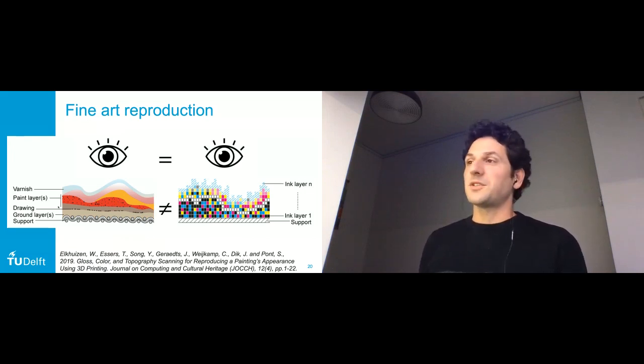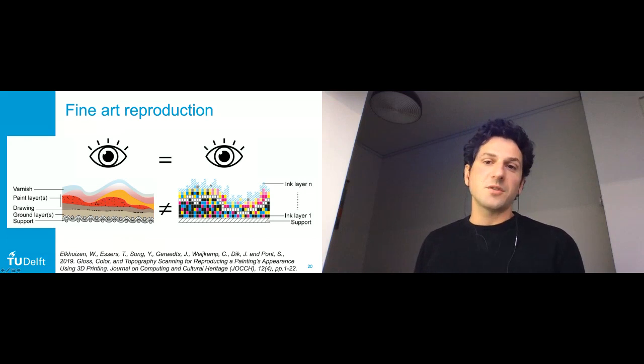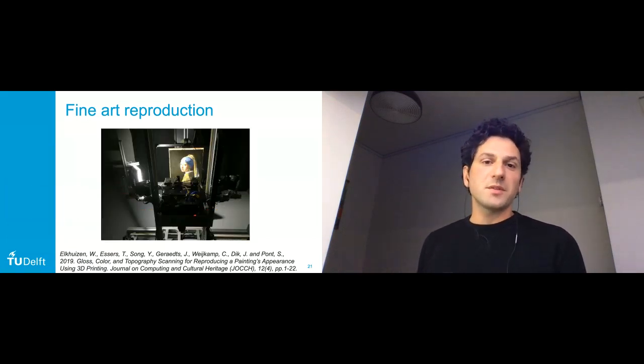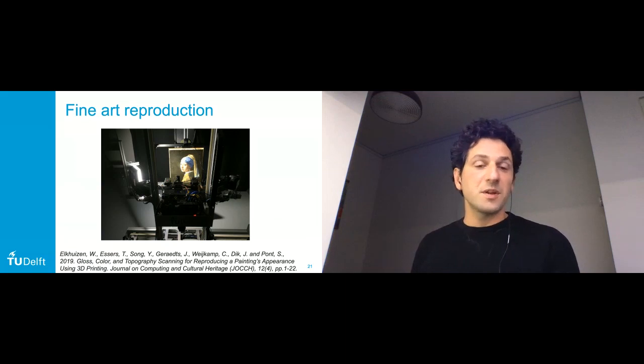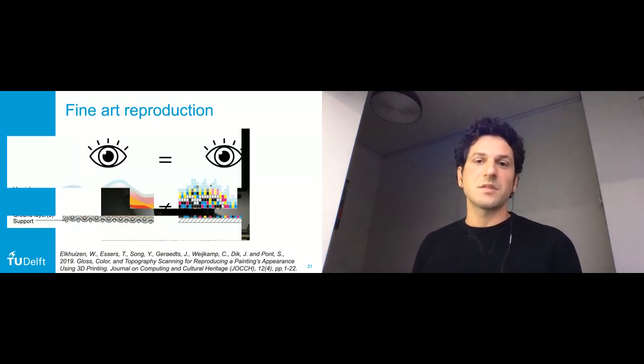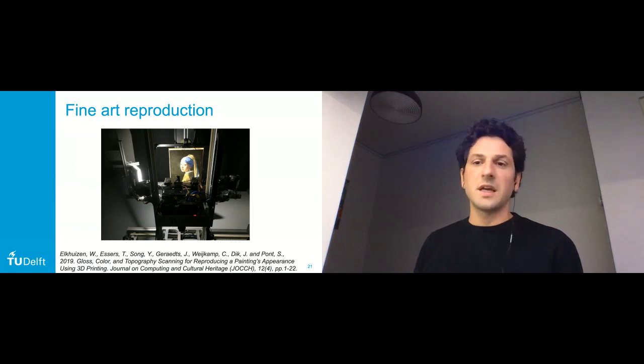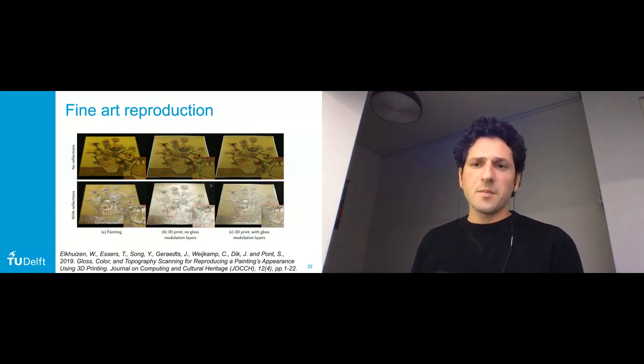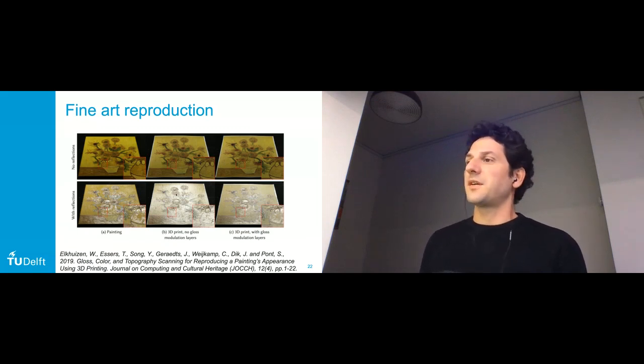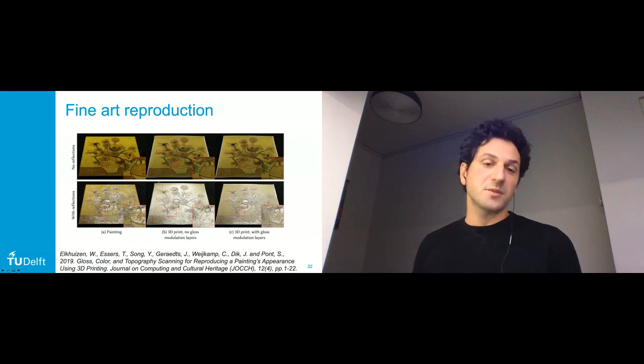And next to just plain color, of course, the texture is important. And in this case, also the gloss variation is essential to replicate. And so to capture these elements, you need also custom-made scanners that capture the texture, the color, and the gloss variation. And the data from this scanner is used to generate the voxel pattern for the 3D printing process, which is also material jetting. It's a different platform, but still a very similar technology that is used. Here you see examples of 3D printed paintings whereby color, texture, and gloss variation was captured and replicated using voxel printing.